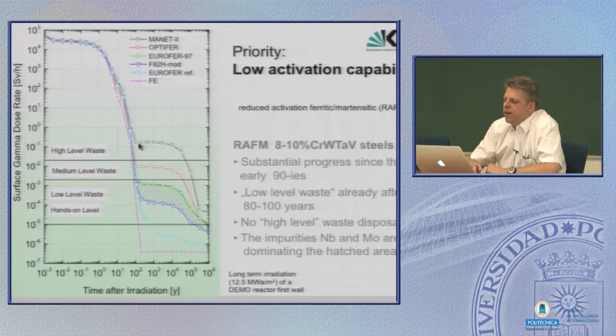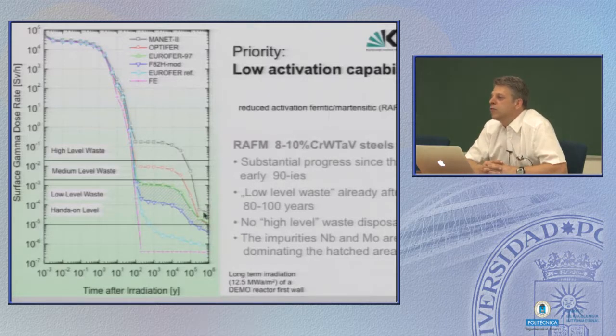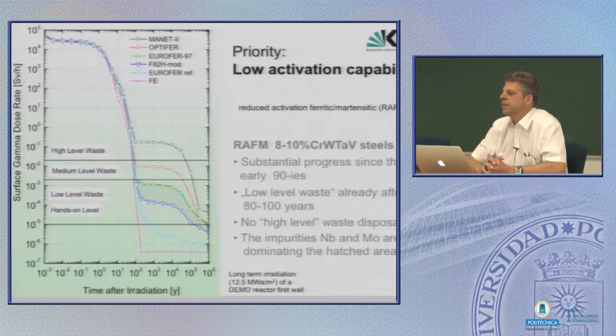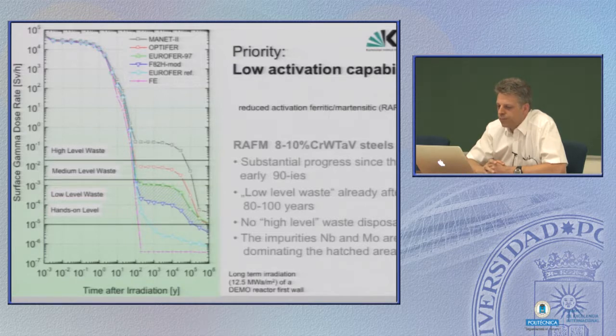And if you would use such a conventional steel, you see it cools down rather quickly after 100 years. But then there is a long living tail in degradation of this activation. And okay, after a few 100,000 years, you could handle this material again. But well, for me personally, this is too long. For you, probably too. So the Eurofer, that's the fusion 9% chromium version, which